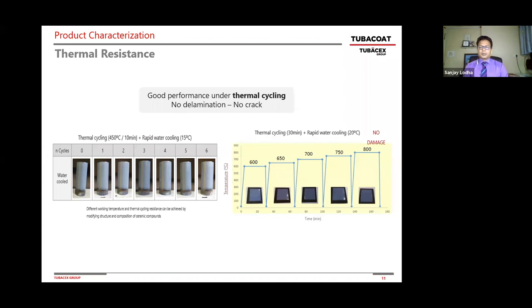On my right side, you see another chart where we take the temperature from 1200 degrees Fahrenheit to 1500 degrees Fahrenheit in intervals. And then we do a rapid cooling to make sure that there is no damage to the coating or there is no delamination, because that's exactly what happens in online spalling. You have a contraction and expansion along with the steam heating and steam cooling. And the coating material expands and contracts accordingly, similar to the substrate. So this property is very important. Next slide, please.